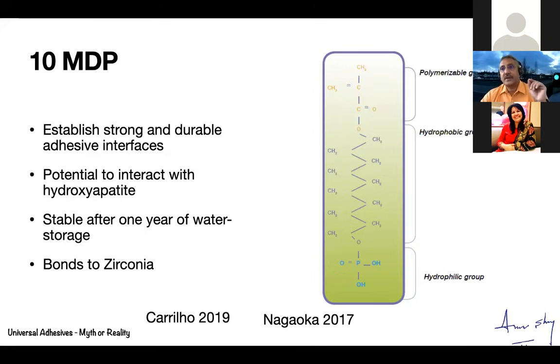The difference is phosphoric acid is very, very highly acidic. And so the salt which is formed is not very stable and it tends to break down. So when you etch with phosphoric acid, you end up with leaching of the mineralized component and you get an etching pattern. Whereas if you use 10 MDP, which is again a phosphate monomer, you get a stable calcium phosphate salt. So this actually can bond to the hydroxyapatite. Not only that, it is stable over a period of time and it also has the potential to bond to zirconia. So 10 MDP makes it a little better in terms of stability of bonding. The type of bonding you get is better and also it bonds to metal. So that's why it is used most often by most of the manufacturers.